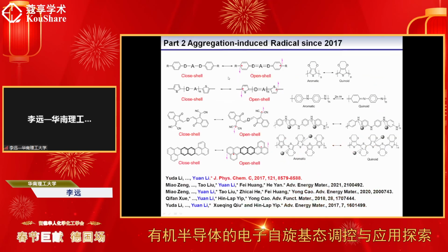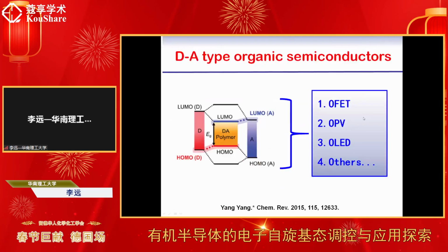In this paper, we studied several small molecules and a series of typical polymers, and we proposed that they showed open shell singlet ground state. Also, we proposed the NFA compounds will also show the open shell ground state. And as we know, the PEDOT and the PANI polymers show the radical cation characters. And almost none of the researchers proposed that the neutral small molecules or polymers show the radical character. And as we know, the DA type organic semiconductors have been very important for OPV, OLED, and OFET in the past 20 years.